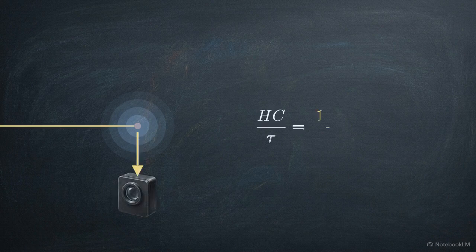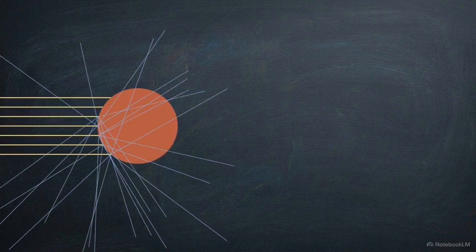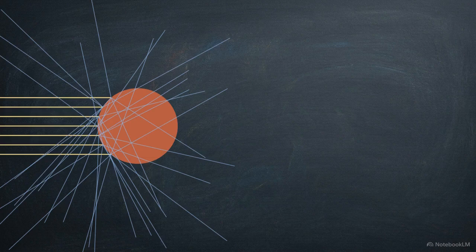particles. This schematic details static light scattering. When light hits a colloidal sol, some of it scatters, causing a visible turbidity known as the Tyndall effect. By measuring the intensity of the light scattered at exactly 90 degrees, chemists use the Debye equation to relate that turbidity directly to the precise molecular weight of the solute. However, the Debye theory breaks down when a particle's diameter exceeds 1/20th of the incident light's wavelength.